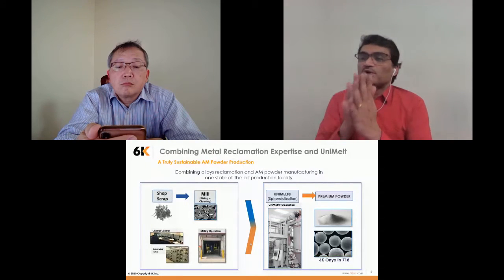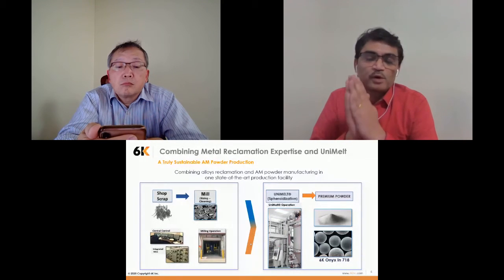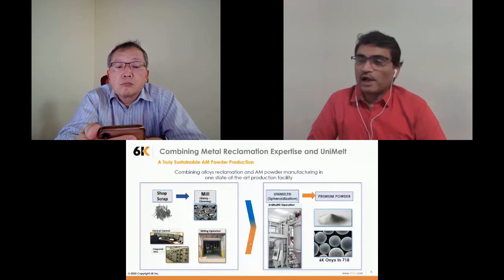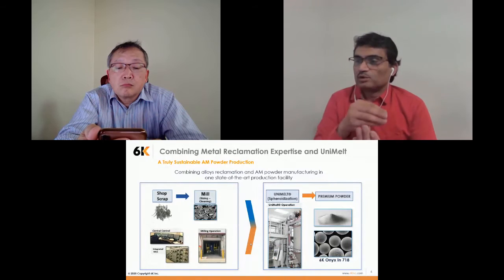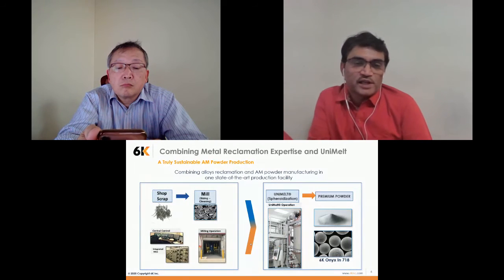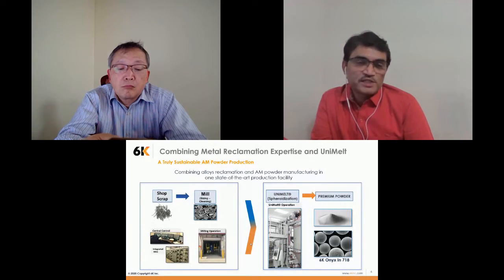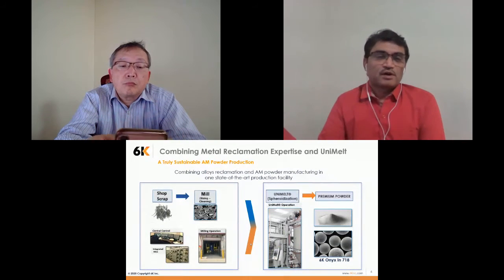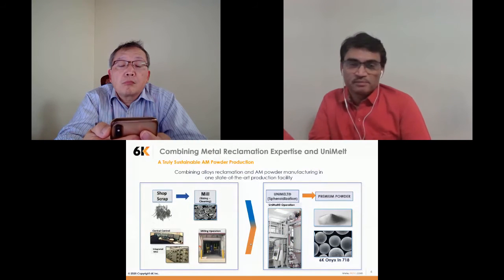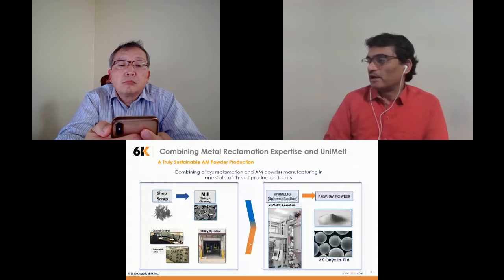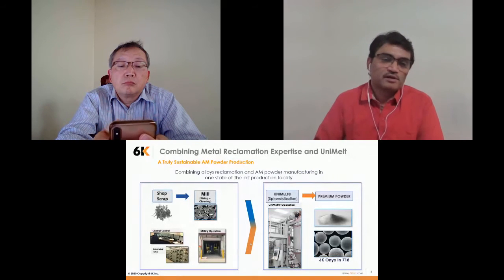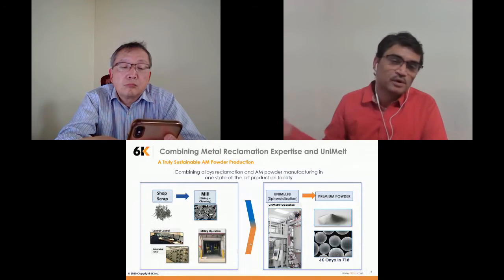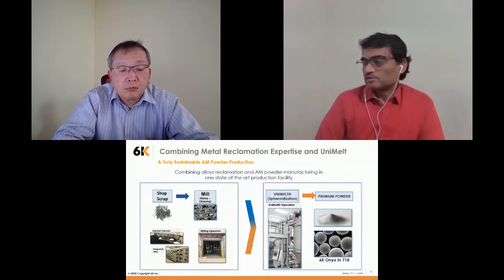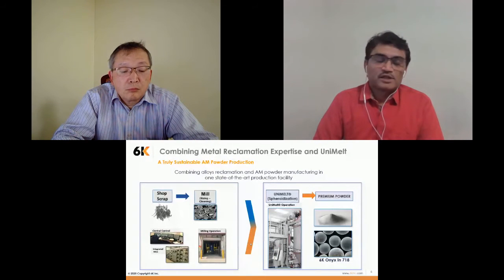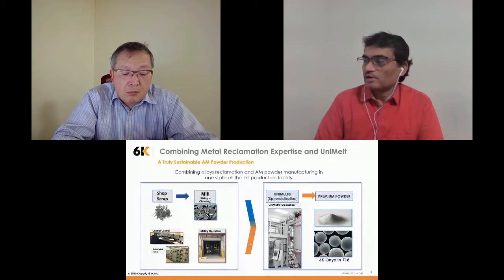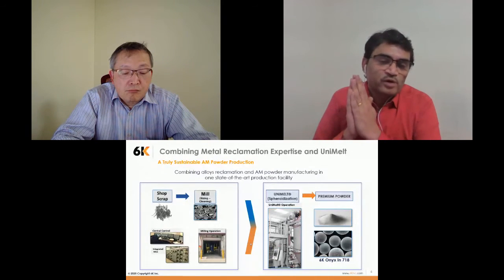So what we have done, we have developed our powder processing or powder manufacturing technology by combining this expertise in this company to process the scrap with specialized milling techniques to desired PSD. And then we use that as a feedstock for our UniMelt spheroidizing system, where we can spheroidize those powders. In this example, it is shown that it is 718 powder right from scrap to final finished powder. We can produce highly spherical powder without any satellites, and with high powder physical properties.